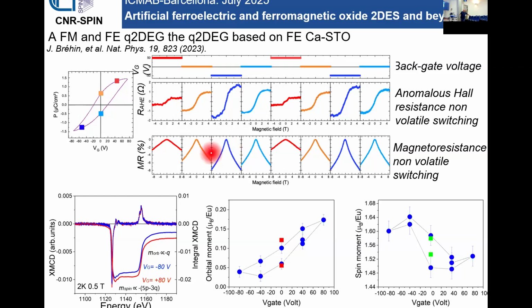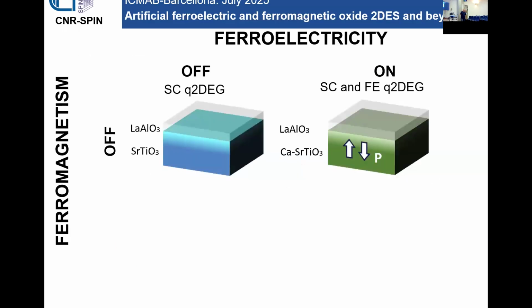More recently, we performed a very complicated experiment, X-ray absorption spectroscopy, in particular an X-ray magnetic circular dichroism measurement, with the gate voltage applied, so in situ. And we essentially found out that both the orbital moment of the europium and the spin moment of the europium are modulated by the polarization, also in a non-volatile way. You can see that there is a non-volatile change in the system. So this is a demonstration of direct magnetoelectric coupling between the two order parameters.